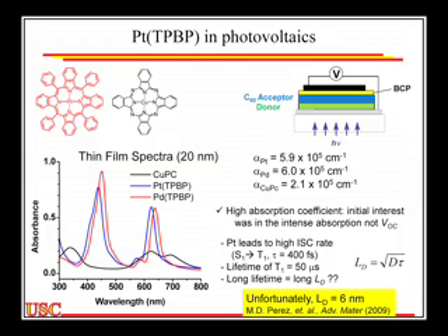And this was a case where two students with adjacent desks actually talked to each other, which was a good thing. So Karsten handed Dolores the sample, and Dolores went and made the devices. And so you can see here, these are thin films. The black trace is copper phthalocyanin, the red trace is the palladium compound, and the blue trace is the platinum compound. And when she first made this, she thought, this is great, right?